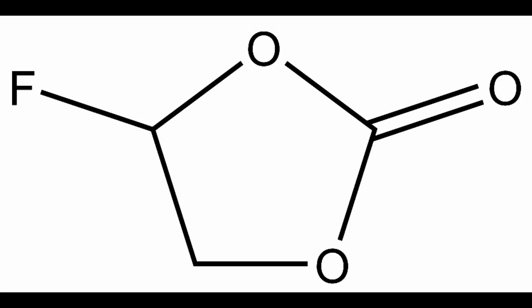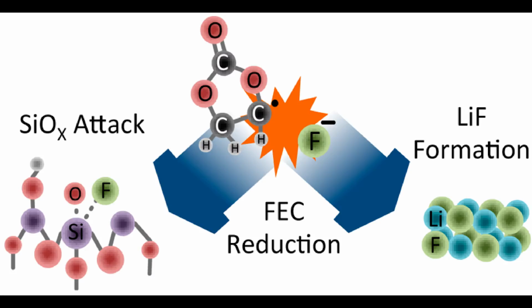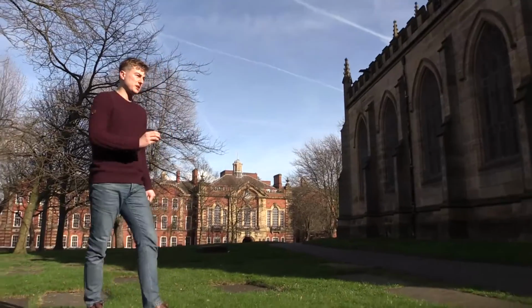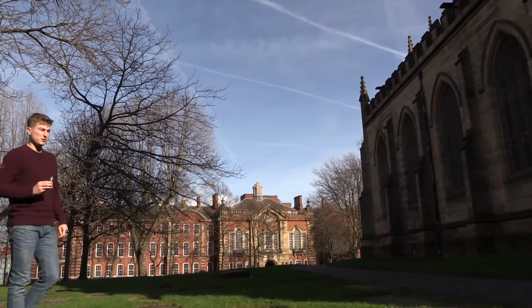So we added FEC to our cells in order to reduce the loss of lithium ions. FEC reacts at the graphite anode, forming a polymer layer that coats the surface. This reaction occurs preferentially to the lithium salt reaction, and hence less capacity is lost during the first charge. Without using FEC, we found our cells to have an average capacity of 92 milliamp hours per gram, and when using FEC, the capacity was 107 milliamp hours per gram, which is a massive 16% improvement.